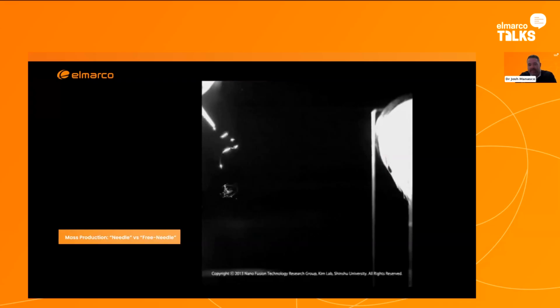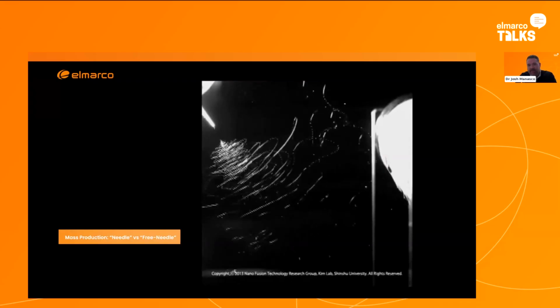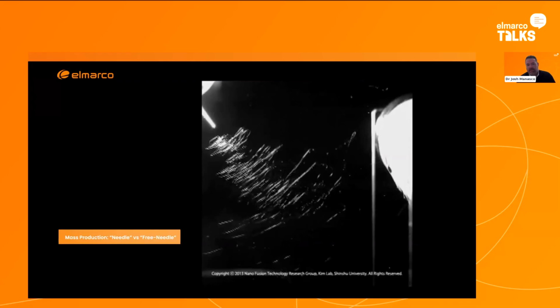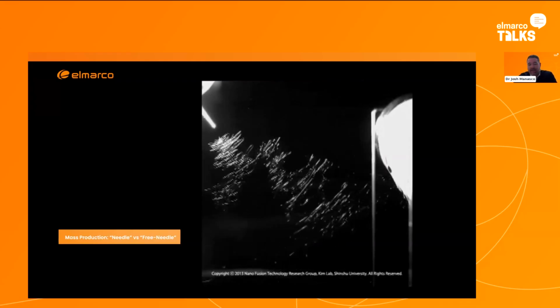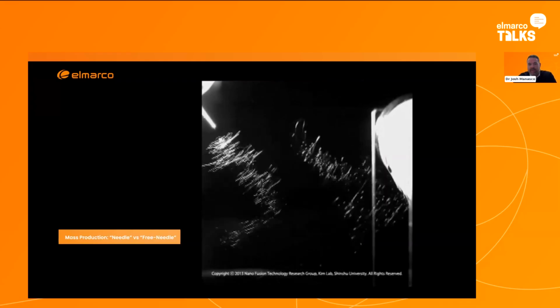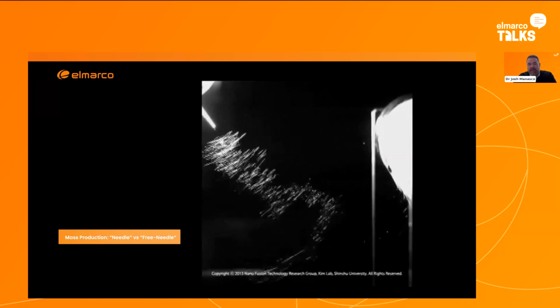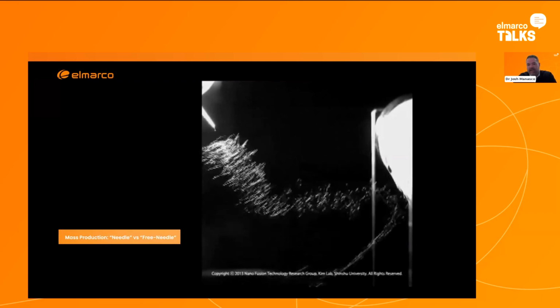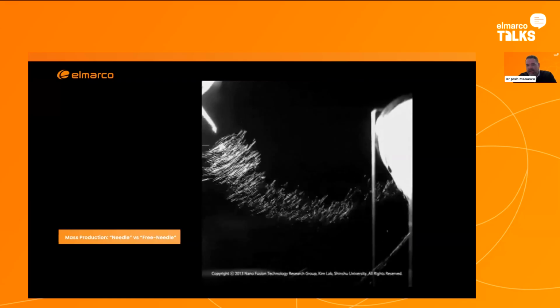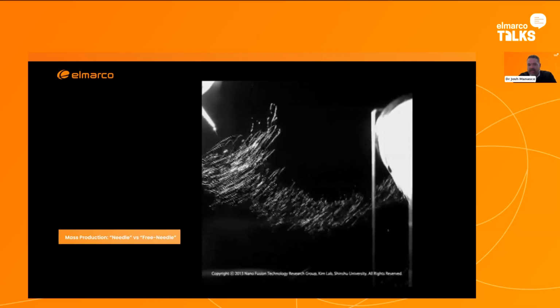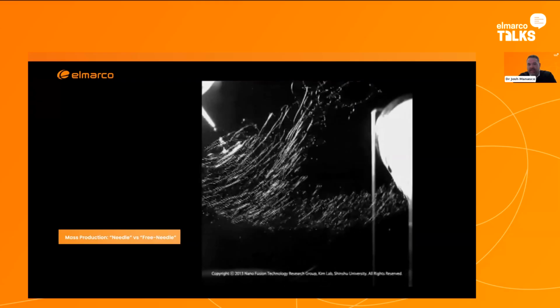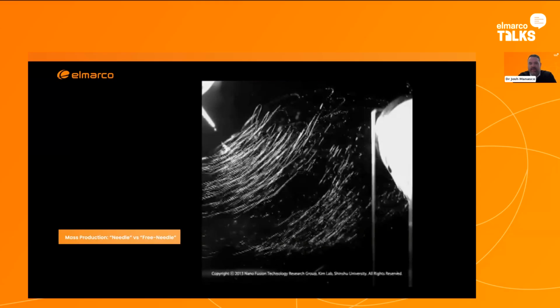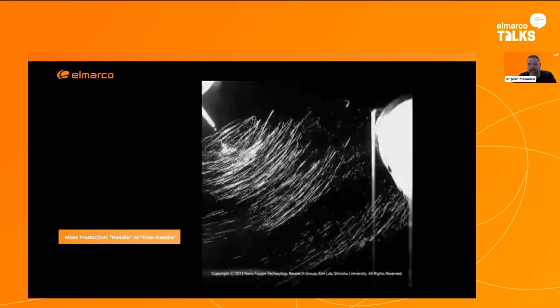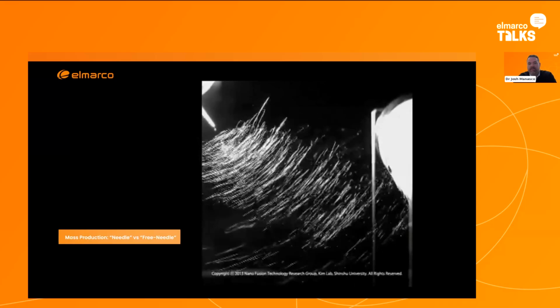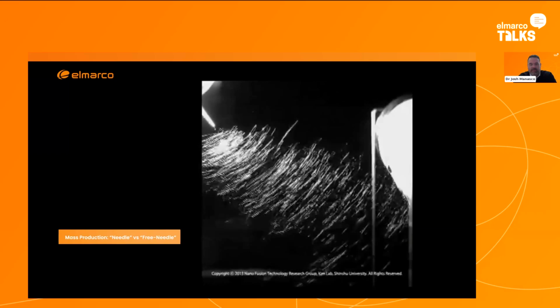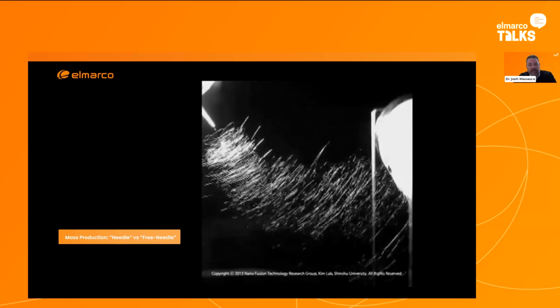And this is just another review. If anybody knows anything about electrospinning, you can see these videos everywhere. Every university in the world has a setup similar to this. You can see that you're defining where the jet's coming from. It's coming from the tip of the needle. It's taking a long path from the tip of the needle to the collector. Either the collector is oppositely charged or grounded in this case. And you can see that the fibers are taking what's called a whipping instability and taking a really long path between the needle tip and the collector where it stretches from sub-millimeter to sub-micron fibers.